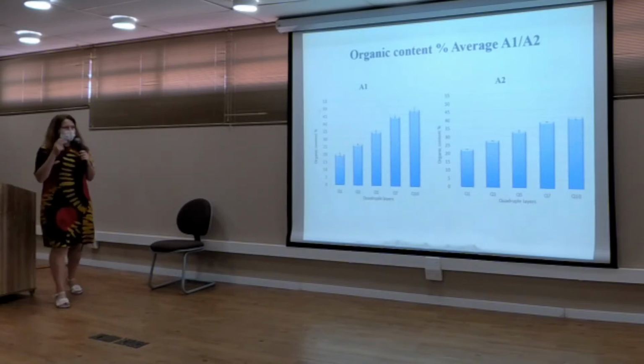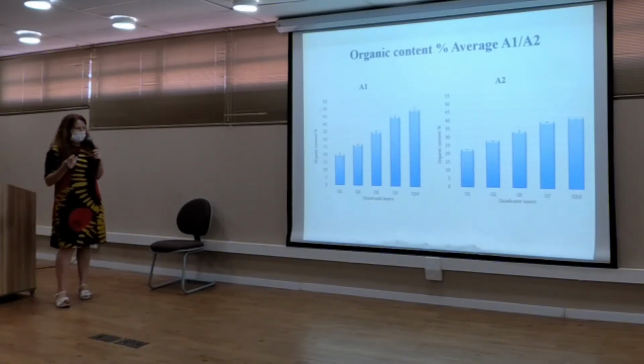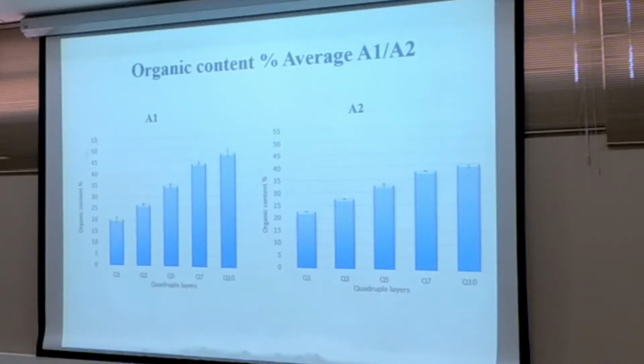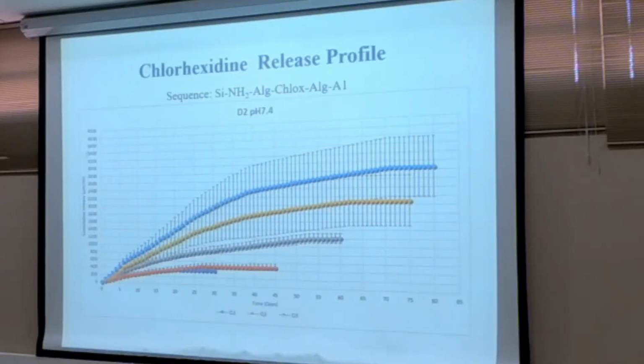Again, I will be brief because the experimentation is similar. We looked at the organic content using TGA techniques, and we looked at the release. Here I will stop because, as you can see, with chlorhexidine you have a much longer release. In some cases, your release can reach 80 days. So it's quite impressive. There is something with chlorhexidine.